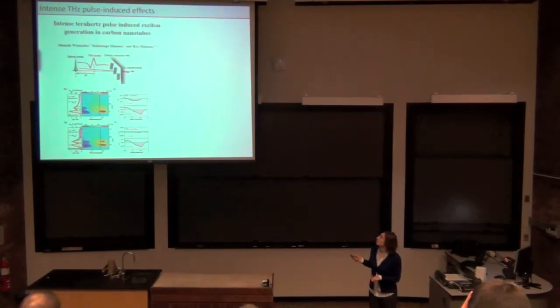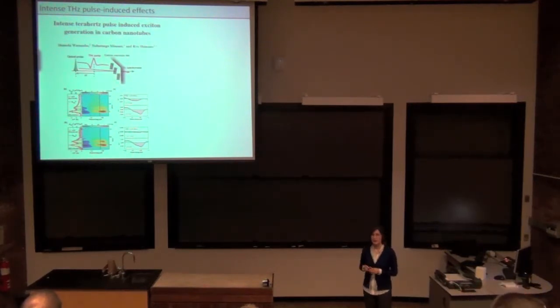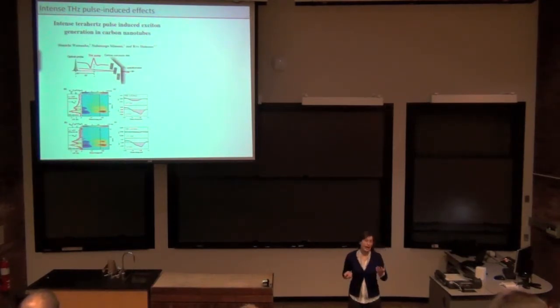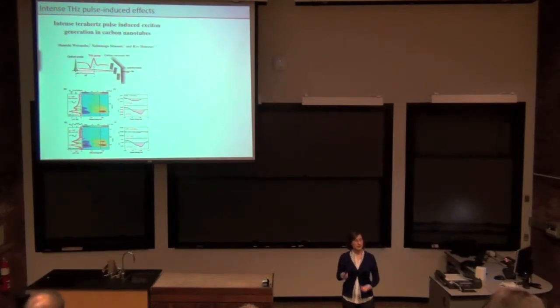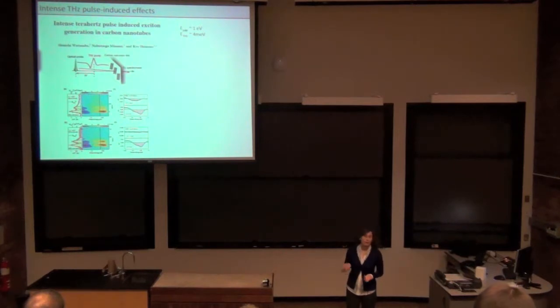Another example was carbon nanotubes. That was a Japanese group that looked at that. They took semiconducting carbon nanotubes with a band gap of about 1 electron volt. They come in with this intense terahertz pulse, and what they see is excitons. How can that happen? Well, the band gap is about 1 electron volt, right? Meaning it's almost